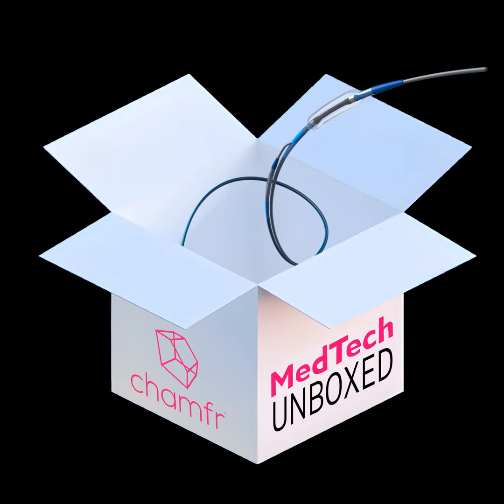Last thing I'll talk about here is testing. Testing with medical balloons is incredibly important. The rated burst pressure is the pressure at which 99.9% of balloons survive with 95% confidence. That's true for balloons used in vasculature. This is defined by an FDA guidance, and the guidance is specifically for angioplasty balloons. But what we found, through our customers, is that the FDA has been enforcing that guidance, that they want us to collect this level of data for the burst rating of the balloon.